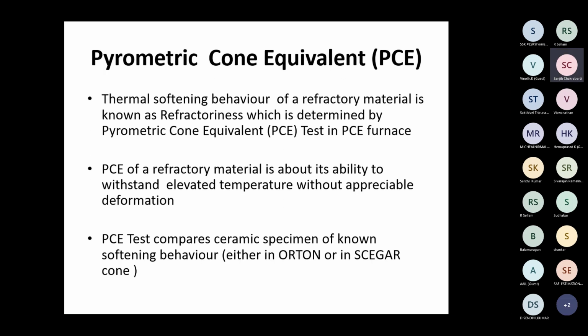Pyrometric cone. The thermal softening behavior of a refractory material is known as refractoriness, which is determined by the pyrometric cone equivalent, or the PCE test. It is done in a PCE furnace. PCE of a refractory material is about its ability to withstand elevated temperature without appreciable deformation. The PCE test compares ceramic specimens of known softening behavior, either in the Orton or the Seger test.